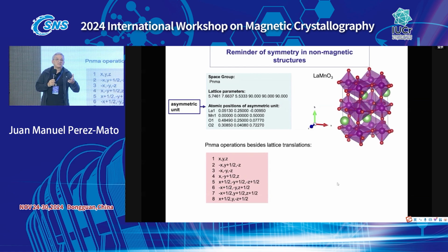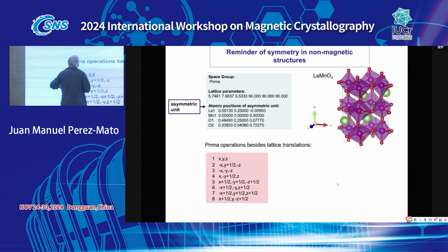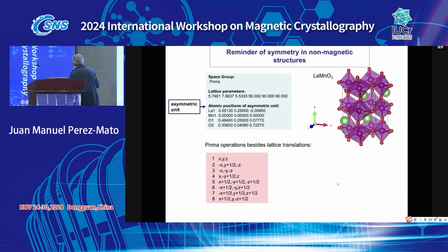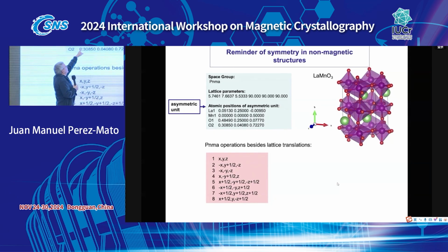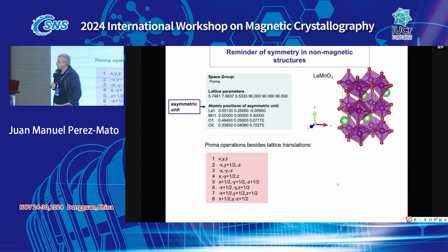And then we apply the unit cell periodicity, and we know that not only these 8 positions, but also some other ones, which, by the way, we will get not 8 positions, we will get 4, because some of these operations will go into the same position. That we say that the multiplicity of this position is 4 and not 8, because a couple of operations do the same thing on the position because of this special value of 0.25, which says that lanthanum lies in a special position.